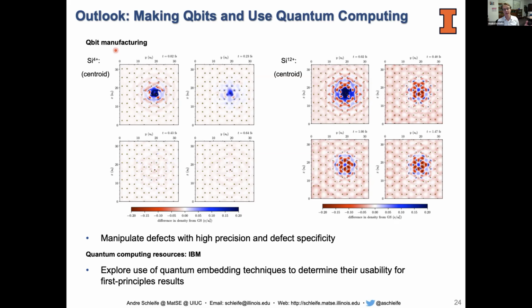So we're just currently investigating some ways to look at how we can make that diffusion directed, for instance, because it's not enough to just get large diffusion of defects. You kind of want to get them in or out of the material, and for that you need to direct the diffusion. So we're trying to figure out how to do that. In this case, you see time-resolved data where we bombard a 2D material. This is graphene again, with silicon of different charge states, and you can see how the following dynamics really depends completely on how highly charged the impact silicon was, right? If it's very weakly charged, the excitation disperses essentially completely, whereas if it's highly charged, the excitation remains, and it remains actually relatively localized. So those things affect the ways to use this effect to create defects in the material and to understand what defect you create maybe and how fast it diffuses and so on.